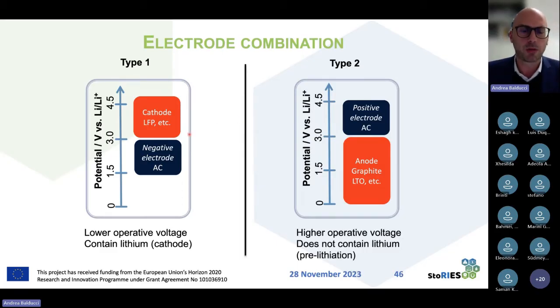One type would be to combine a cathode of lithium-ion battery with an anode of supercapacitor. That means we can take, for example, a cathode of a battery like lithium iron phosphate or NMC, where you have already lithium inside, because the cathode is the source of lithium in lithium-ion battery. And then you use as a negative electrode, not graphite like in lithium-ion battery, but an activated carbon. This system would be quite easy to implement. Of course, we need to work on balancing, but they already have basically everything they need. You could use an electrolyte for lithium-ion battery. The lithium is inside the cathode, and then you could operate them if you find a good balance.